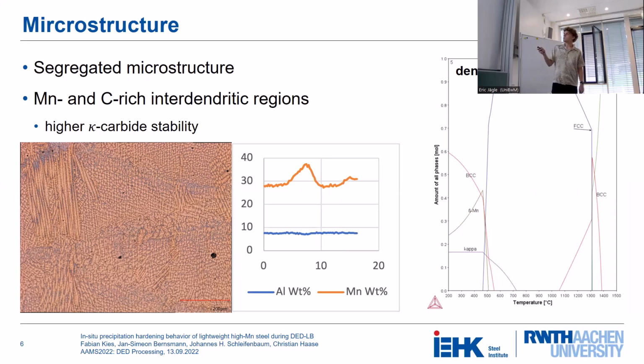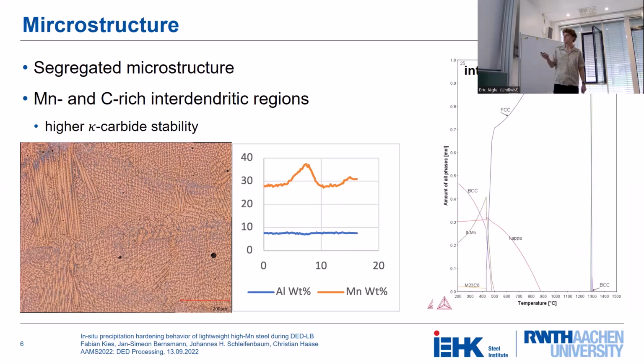So I brought you two CALPHAD calculations, one for the dendrite core, so the manganese-poor region, where you can see that kappa-carbides are a lot less stable and also are only precipitated to about, let's say, 650 degrees C. Whereas in the interdendritic region, you can see the higher manganese content leads to a higher stability of the kappa-carbide phase, which can be precipitated to, let's say, 800 degrees C, and even with a high volume fraction.